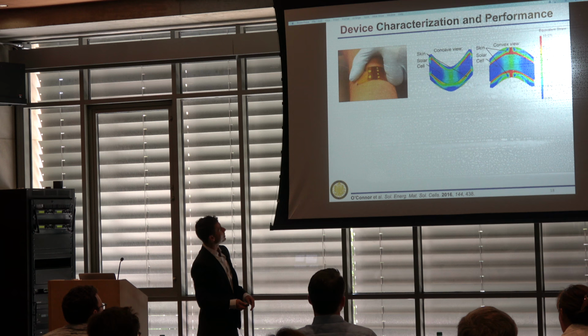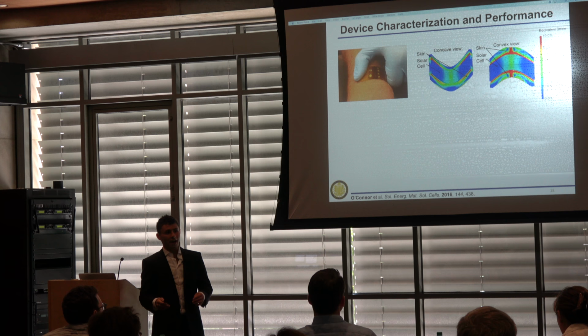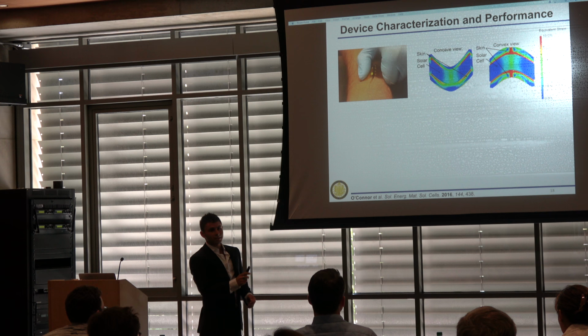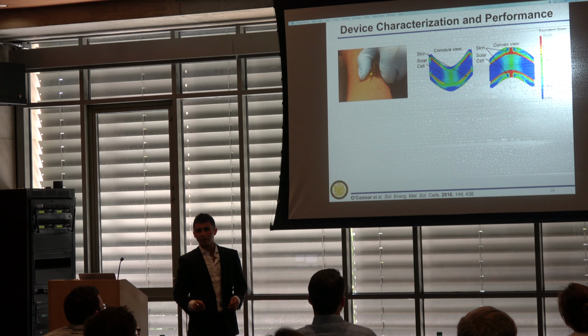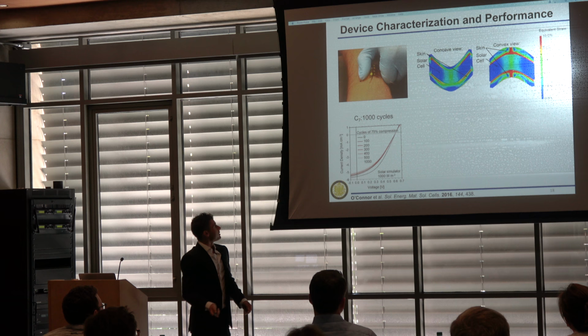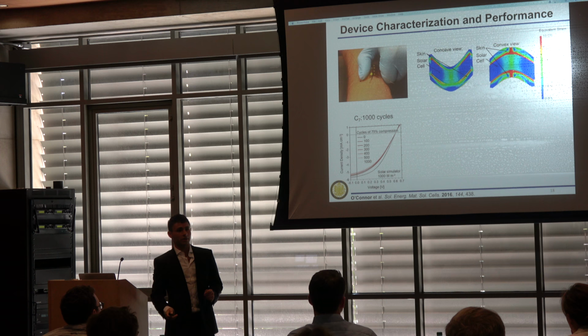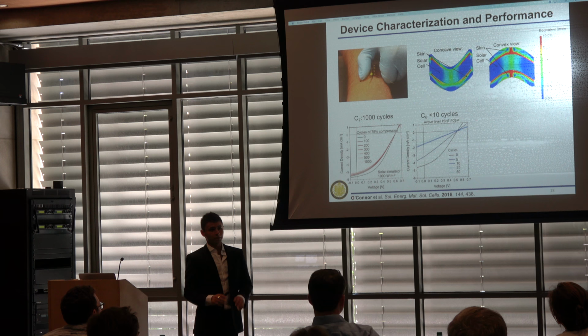We used all of these different materials design rules in order to judiciously choose each layer for a mechanically resilient solar cell that we could put on the human body. We smashed it, compressing it by 75%, 1,000 times. We used finite element analysis in order to predict the strain and the strain distribution on the surface of the device. So the devices would need to accommodate 5% strain in order to function without destroying the cell. So cells using C70, after 1,000 cycles, still maintained over 80% of their initial performance. And as a comparison, C60, after just 10 cycles, the device was destroyed.